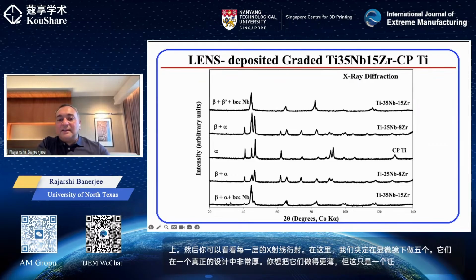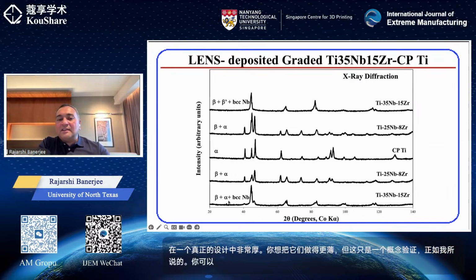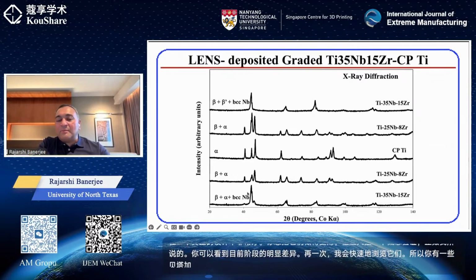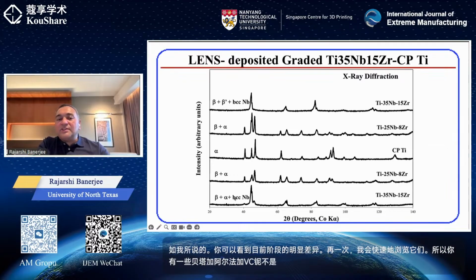And you can see the distinct differences in the phases present. Again, I'll just quickly go through them. So you had some beta plus alpha, plus this BCC niobium, which was unmelted niobium powder. This is what gave rise to these peaks, and they happen to occur when you had the highest niobium. So there are no surprises there. But bottom line, you got the BCC phase, some alpha phase coming in, and the fraction of alpha phase, which is the HCP phase, increases as you go to CP titanium. CP titanium, by the way, is going to be 100% alpha because there is no BCC stabilizing element in that.